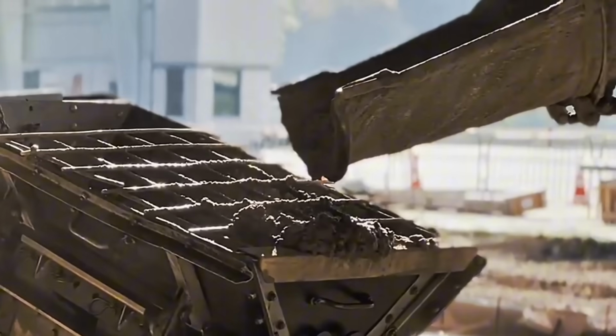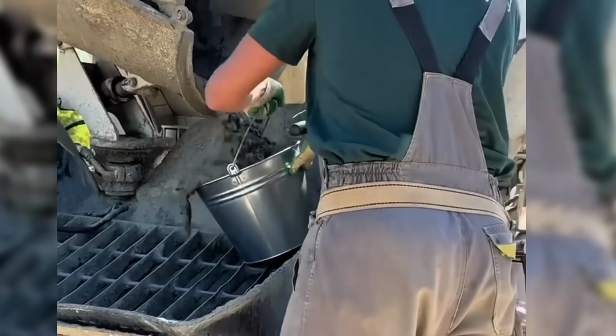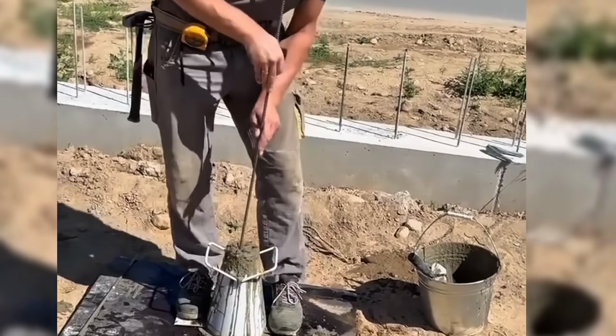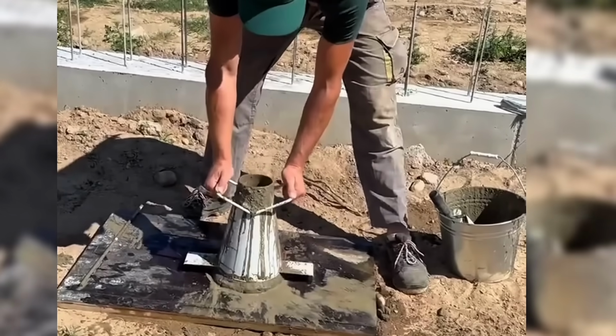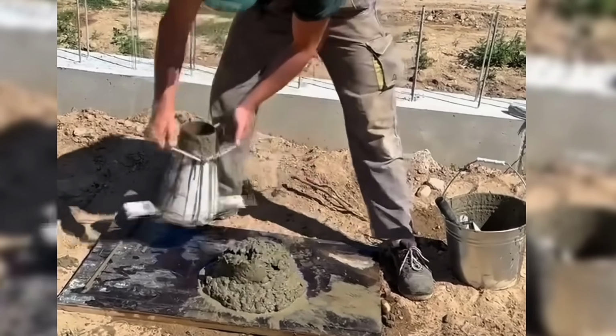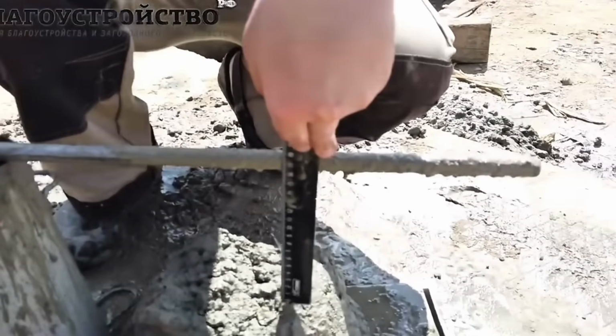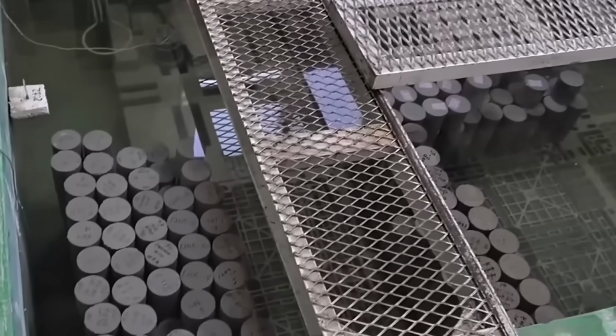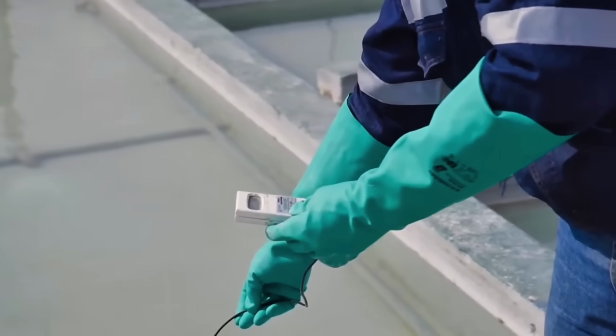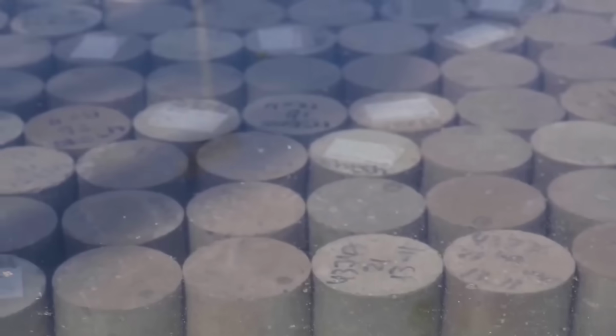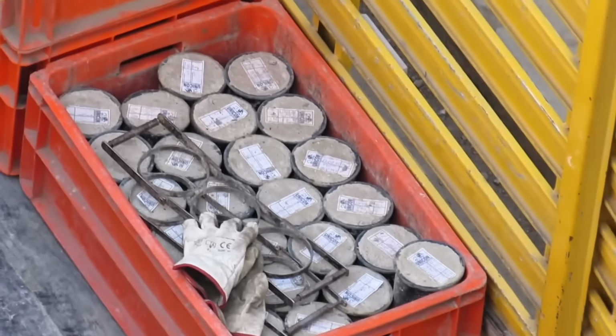When you see neat concrete cylinders near a mixer, those aren't waste. They are control samples cast from the same batch as the main pour. They are left on site to begin curing under real-world conditions and are later sent to a lab for compression strength testing. Before testing, the samples are cured in a controlled environment to ensure the concrete reaches its design strength, usually at the 28-day mark.